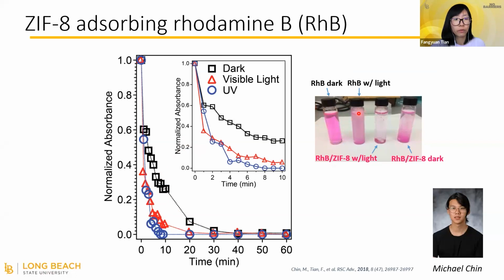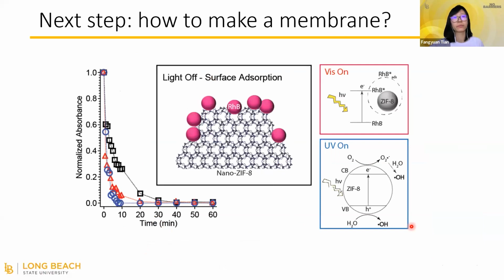And when we placed the ZIF-8 nanocrystals in there, stirring it with light or without light, you can see that even in the dark condition, after 30 minutes, all of those pink dye will be gone. And for the UV condition, even after 10 minutes, the pink color will be gone.